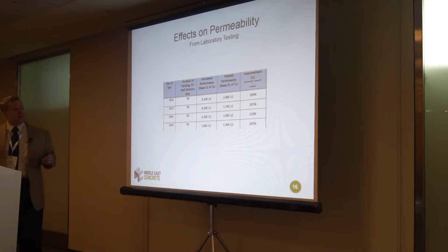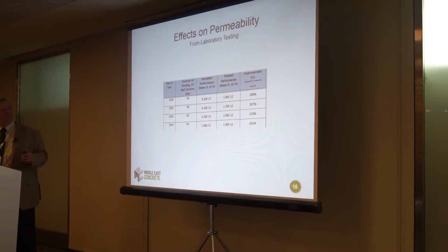Since this was done, I've begun running some permeability testing using a new test standard called, or it's new to me, it's not that new, NT492, NordTest 492. Does anybody have any experience with NT492 in the room? All right, NT492 is a very fast electrostatic way to pull chlorides into the concrete. So you have calcium hydroxide and sodium hydroxide on one side, sodium chloride, salt water on the other side. You induce a voltage, and then you can pull chlorides into the concrete and then measure the chlorides and how quickly. So it makes a comparison between untreated concrete and concrete treated with colloidal nanosilica. It makes it very fast and very easy to determine how well the concrete's going to improve.